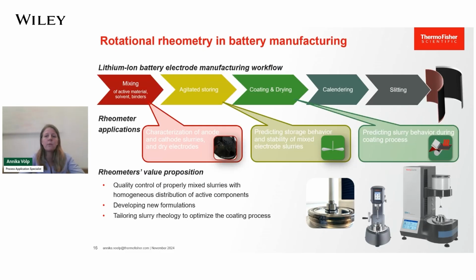Here we outline the manufacturing workflow of lithium-ion battery electrodes, emphasizing the crucial role of electrode slurry rheology as a quality parameter. Rheometers serve as widely adopted quality control tools, particularly for the characterization of the viscosity shear rate dependence of both anode and cathode slurries. This characterization is essential as it predicts dispersion stability during storage of the slurry and the behavior during the coating process. Rheometers are utilized for various purposes: ensuring the proper mixing of a slurry for quality control, facilitating the development of new formulations, and for tailoring the slurry rheology to optimize the coating process.